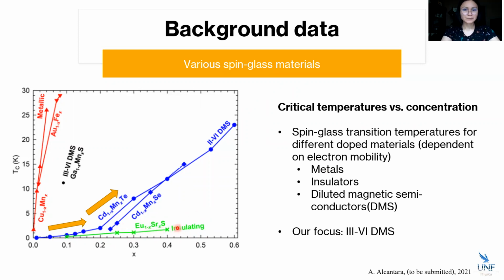And then down here we have the insulators, which are very stable in their configuration. So they require larger levels of doping to induce a decent transition temperature. And then if we look at the diluted magnetic semiconductors, you can see this is kind of a sweet spot for the transition into a spin glass. And what's most prominent here is that there is a shift in slope after about 20% doping, and we found this interesting, and that's why we wanted to take a look at diluted magnetic semiconductors for this study to see if we can dope something above 20% to see if anything in the electronic system is happening. The reason why we decided to do this is because we know what materials can transition into the spin glass, and we know what temperatures, but we don't exactly know how they're transitioning into a spin glass.